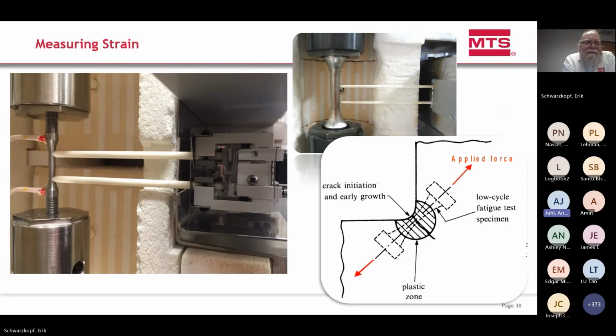When you have aggressive environments -- furnaces, hot or cold or corrosive -- you need some other kind of extensometry to measure localized strain. Here are some examples: ceramic arms that go through the walls of the specimen, able to withstand the heat the specimen sees, touching the specimen to measure strain locally.